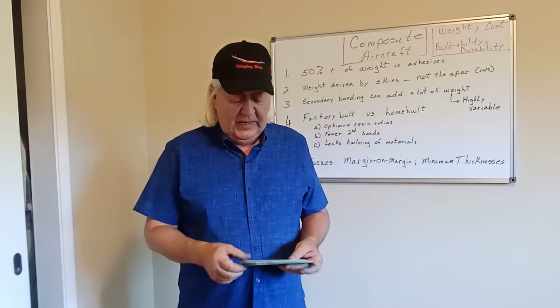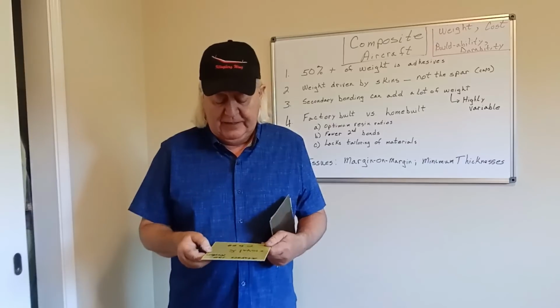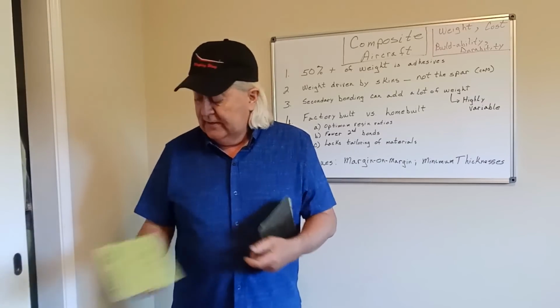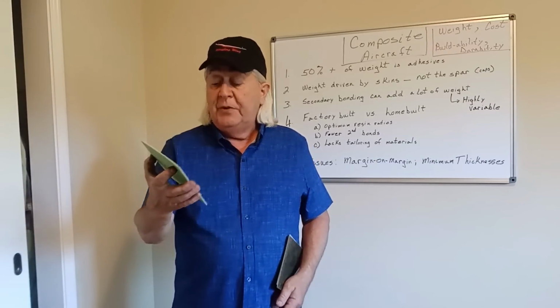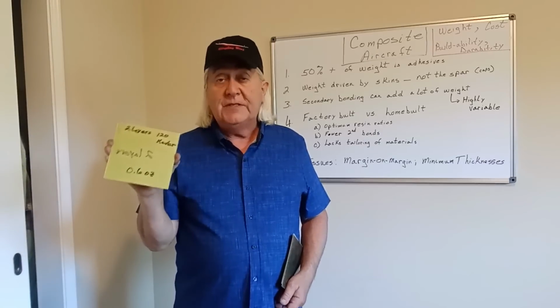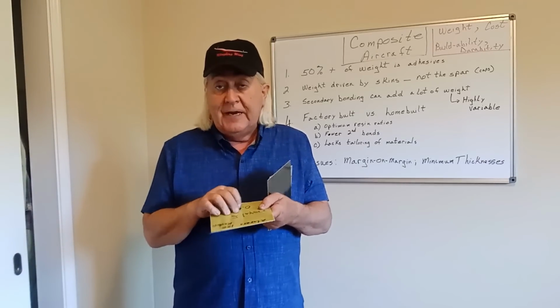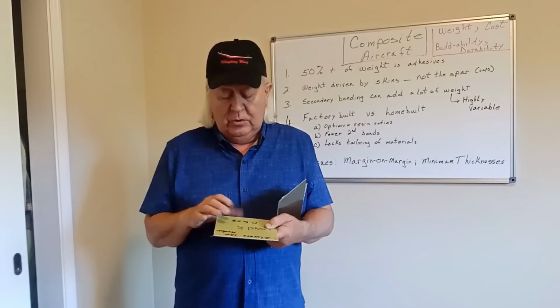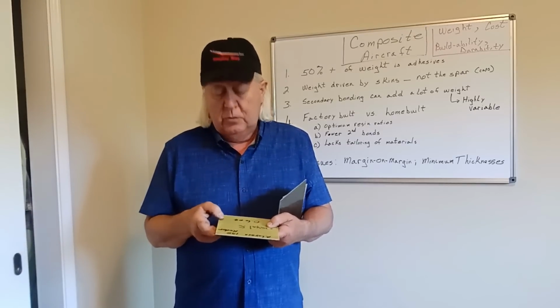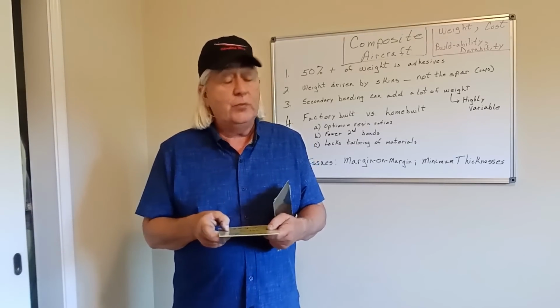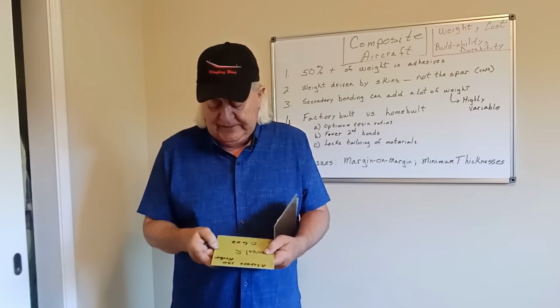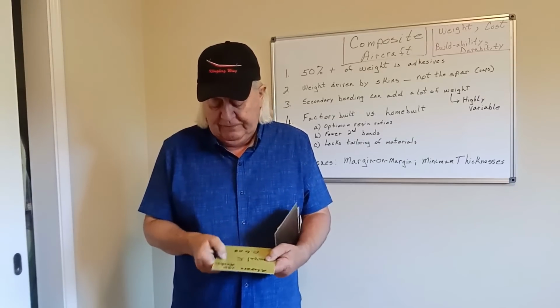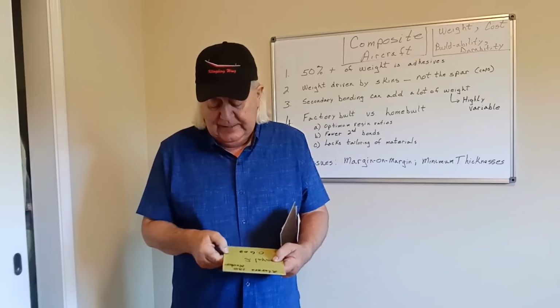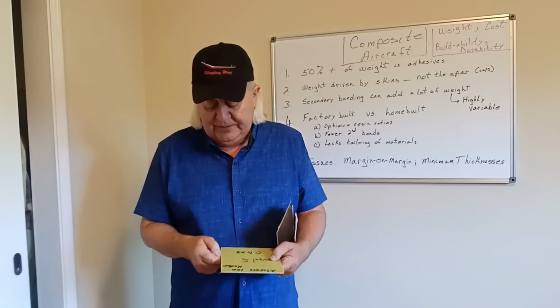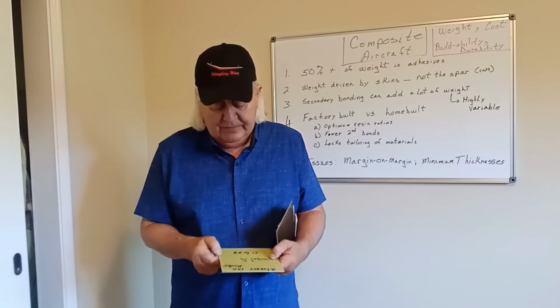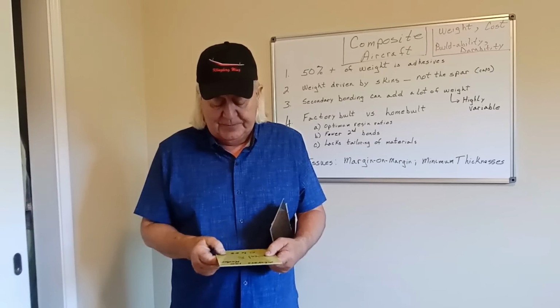And then I did 2 layers of 120 Kevlar, same layup, but 2 layers of Kevlar, and that's 0.6 ounces. This is essentially the layup they have on the outside of the Swift, or on the early Swifts. I don't know what they're doing on the Swift 3 version. And this is practically bulletproof for denting. I can make a mark, but it bounces back. It's Kevlar, you know. Kevlar has that amazing ability to bounce back.